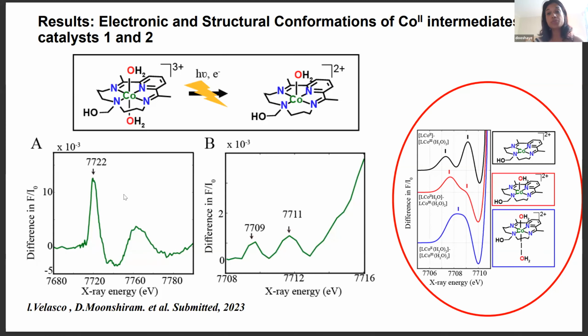Interestingly, we not only observe changes in the oxidation state of the photoreduced complex, we also observe changes at low photon energies at around 7709 and 7711 eV, which corresponds to the typical pre-edge of the cobalt-2 intermediate. All of our experimental results are generally corroborated with TDDFT calculations.